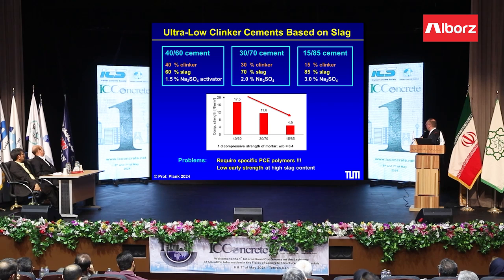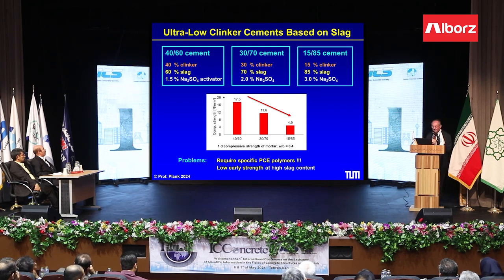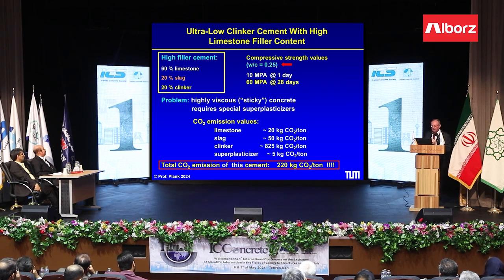And the problem with reduced clinker content is that the strength gets lower. This is the one-day compressive strength, and so we need to find a way to increase the strength, and the easiest way is to reduce the water to binder ratio. But then you have a workability problem, and this is where the superplasticizer comes in.